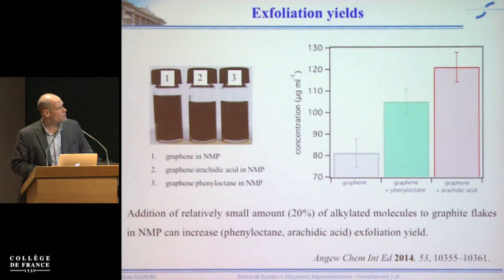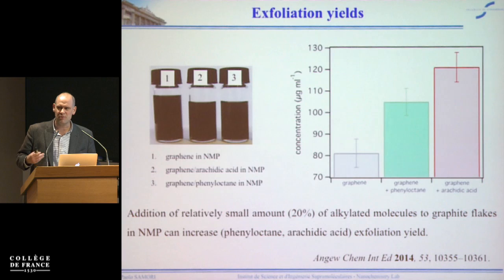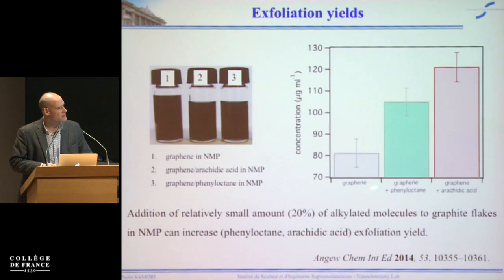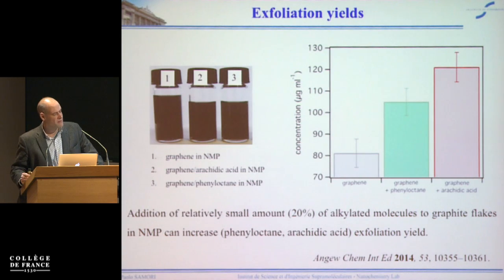Now, just a snapshot to show that you can quantify the yield of exfoliation, so the amount of graphene you can bring in solution. And you can see that if you compare the exfoliation of graphene in pure NMP with the one obtained with phenyloctane or arachidic acid, there is a gradual increase of the exfoliation yield up to 50% when you use arachidic acid compared to pure NMP. And so this is due to the role of the van der Waals interaction between molecules adsorbing on the basal plane of the graphene and stabilizing the graphene phase once exfoliated.